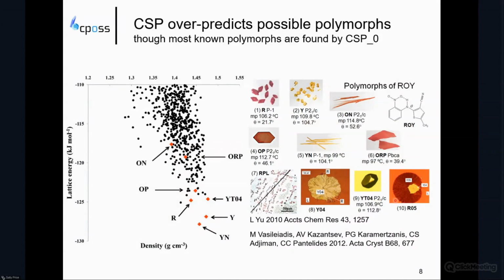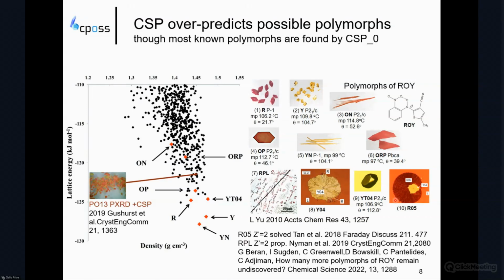Now, since 2014, a couple of those structures have been solved, Z prime equal 2. Another one was found, pumpkin orange, in 2013, where from the powder pattern, perhaps you can see the crystals, you've got some yellow ones mixed in with the new form there. Solving it from the powder pattern was helped by using the CSP results. But nonetheless, when far superior and more accurate computational methods were used for the energy in 2022 to revise this landscape, they nevertheless came out with the conclusion of how many more polymorphs of ROY remain undiscovered. And I think they're up to 13 now. They keep on being found, but there are so many more being generated by the calculations than are known.